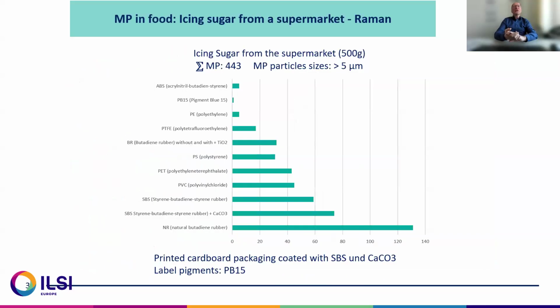Third example, icing sugar, also from the supermarket, 500 grams, and here we found around 440 microplastics and pigment particles. Here it was the same. The printed cardboard packaging was coated with SBS, so we found SBS here also, but here not so many pigments. Maybe it's another factory, and the ambient air was better cleaned. The reason for the high content of natural rubber is until yet not clear in this packaging. Maybe it comes from seals which are used in the filling station or so.